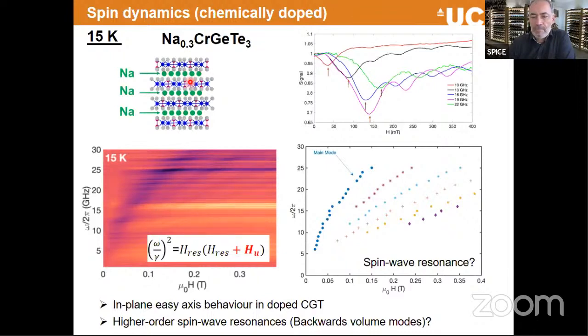Thank you for this excellent talk and these nice results. Just one comment first. You can determine the Curie temperature at a ferromagnetic transition with the critical fluctuations which you see in the FMR damping. So if you monitor the line width as a function of temperature, you might see the feature of critical fluctuations. But my question is, when you do this doping, I would assume that you have strong spin-orbit effects, which would mean that the g factor or g tensor should change in your material. Did you investigate that?